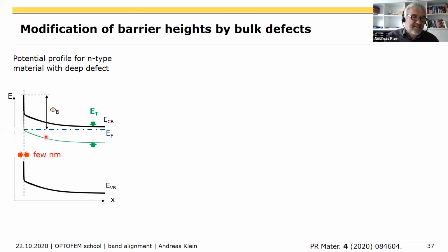As soon as this trap level is crossing the Fermi level, you start to occupy the traps. And that means you change your effective doping concentration of the material considerably. And that means the space charge region is just shrinking. The width of the space charge region is then very much shrinking.